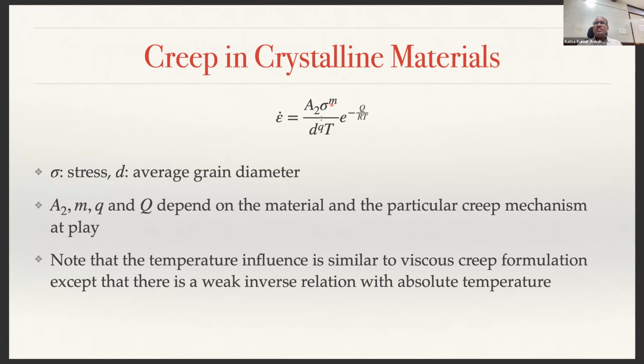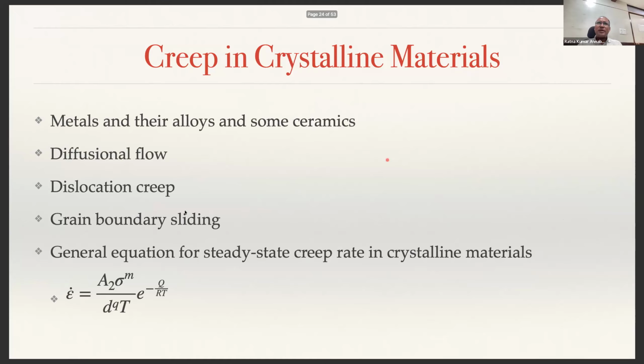Sigma is your stress, d is your grain size, because the creep deformation also depends on the grain size. If your grain size is smaller, there are more grain boundaries, and hence grain boundary sliding is more active, so the grain size also comes into the picture. A2, m, q and capital Q are all material dependent and depend on the particular creep mechanism at play. What do I mean by particular creep mechanism? Whether it is diffusional flow, dislocation creep, or grain boundary sliding.